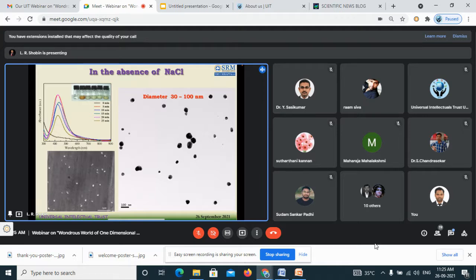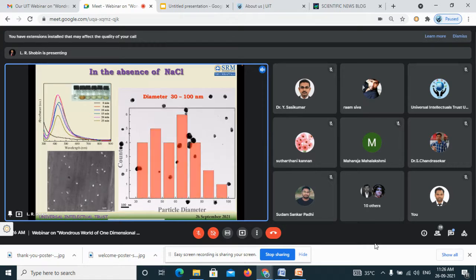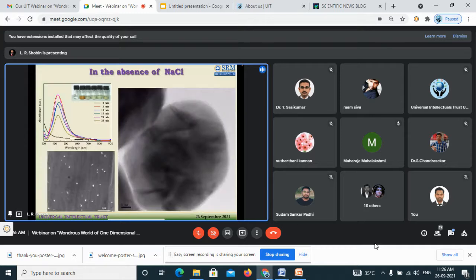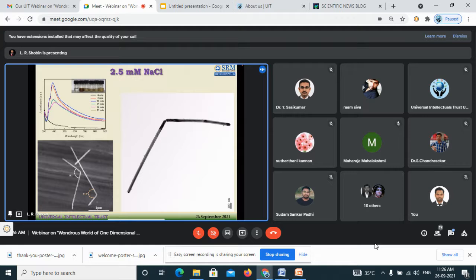These particles have a diameter ranging from 30 to 100 nanometer. They are all small in nature. You can use this process for synthesizing nanoparticles also. If you're really interested in nanoparticles, you can use this process. Very simple process. You take a silver precursor, put it in glycerol, and heat it up for 25 minutes. You can see the color change, and you will end up with the particles. We have found the particle diameter range also. These particles are polycrystalline in nature, and they have very thin crystallographic boundaries.